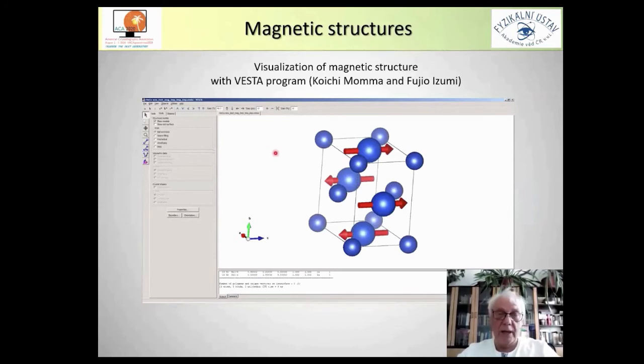For modulated structures, magnetic modulated structures, we have problems because Vesta does not support superspace symmetry. But then we can use an option in Jana where we can create a large, artificial cell, which takes into account that in each discrete cell the position is changed by modulation.